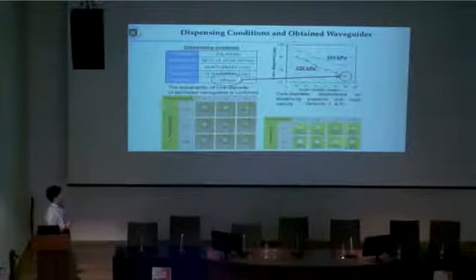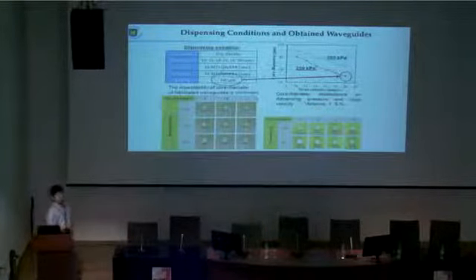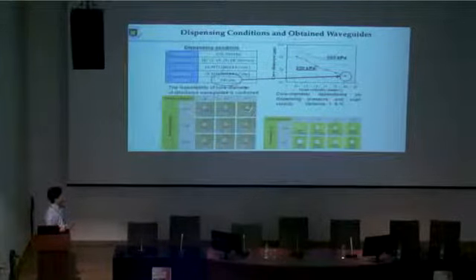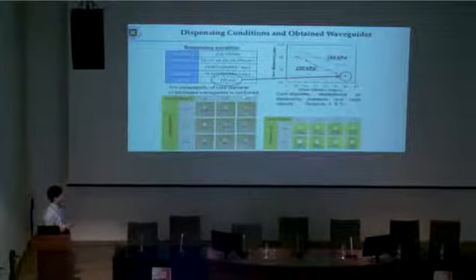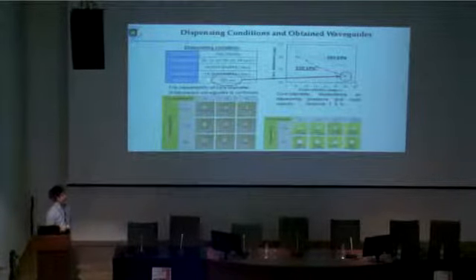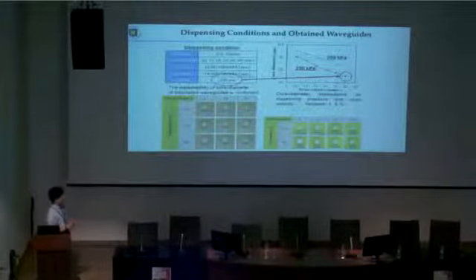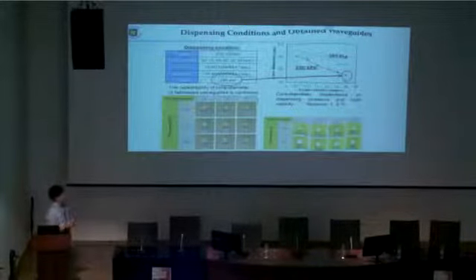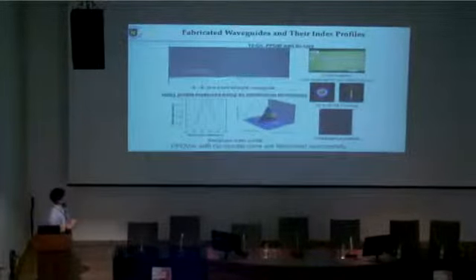And when we use a smaller inner diameter needle, in this case 150 micron, we could reach less than 50 micron diameter core. And circularity is very good. And by changing the dispensing conditions, we can obtain not only a smaller core, but also a larger core. And here is the obtained waveguide.